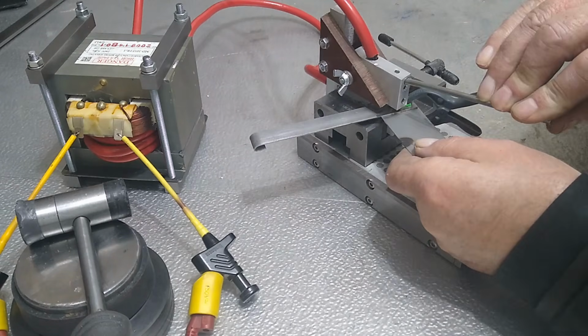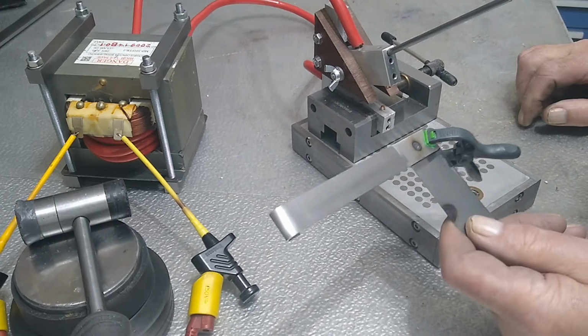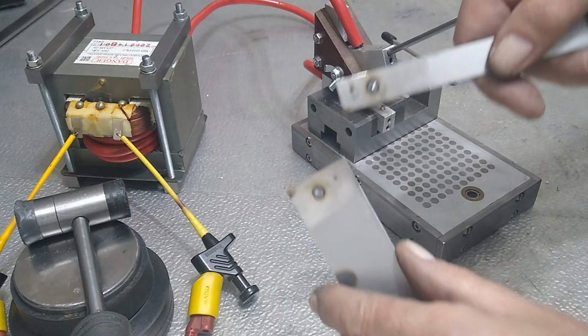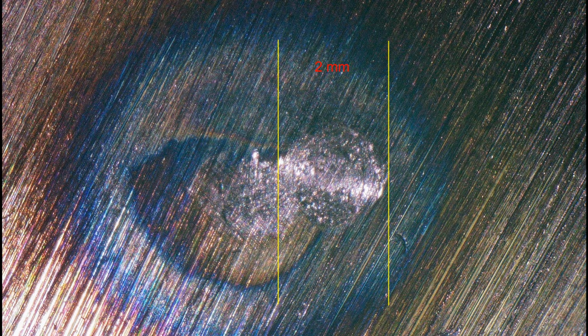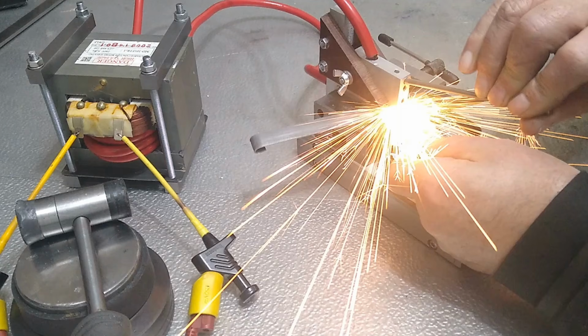Let's do the same little test again, now with 2 plates 1mm thick. After no less than 2 seconds, the weld is still very weak and the material has clearly not melted deeply enough. It does, however, produce a wonderfully dramatic shower of sparks. The kind of shot a YouTuber might be tempted to use as a thumbnail. Purely for scientific reasons, of course.